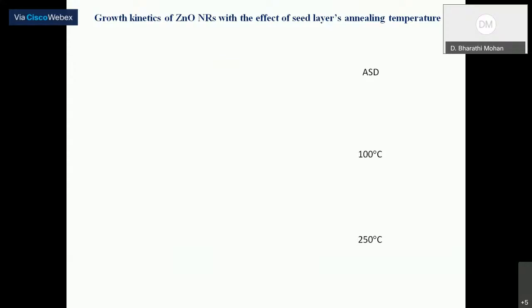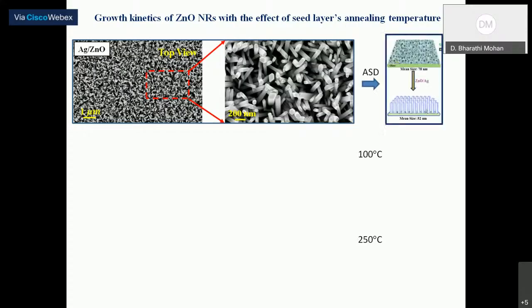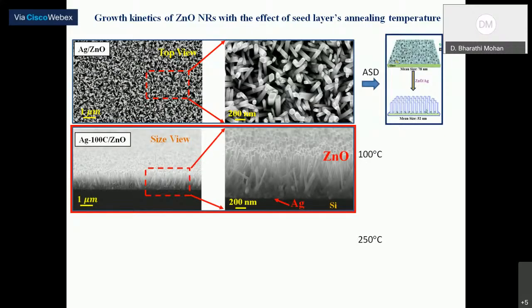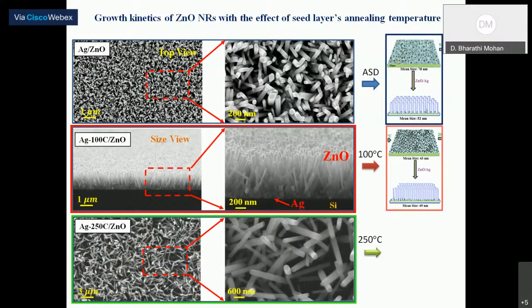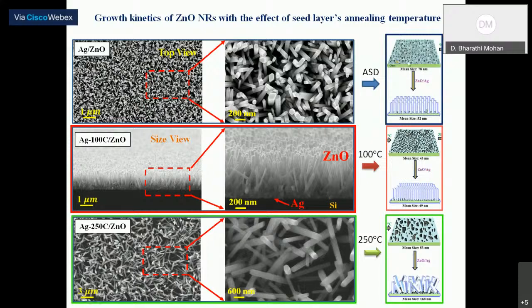Now let us understand the growth kinetics of the zinc oxide nanorods and the effect of the seed layer's annealing temperature. The growth of the zinc oxide nanorods is understood on a different platform. For example, the as-deposited film is in a quasi-amorphous state. So when you grow zinc oxide nanorods through the hydrothermal process on as-deposited silver film, you grow vertical zinc oxide nanorods, but they are loosely dense.